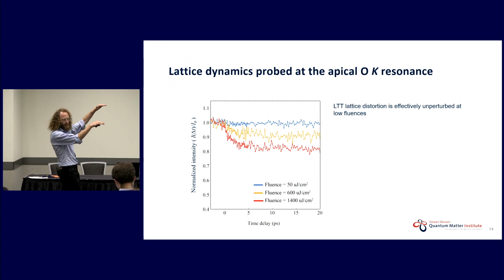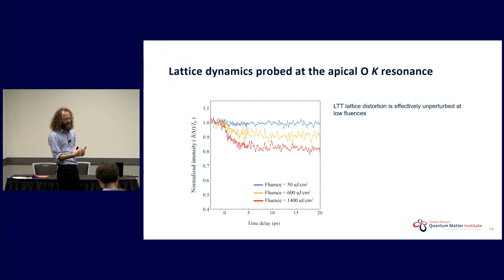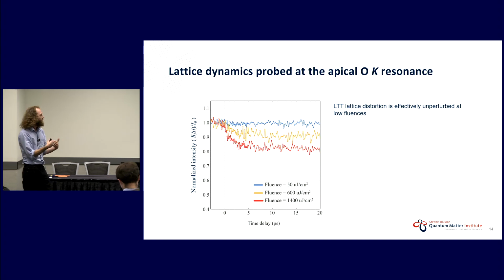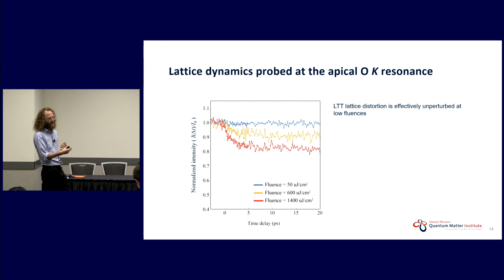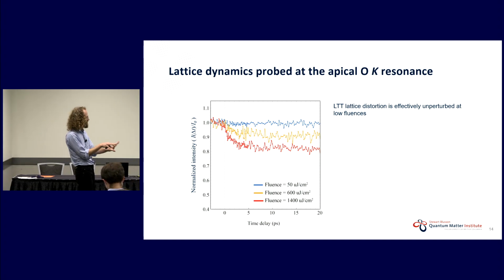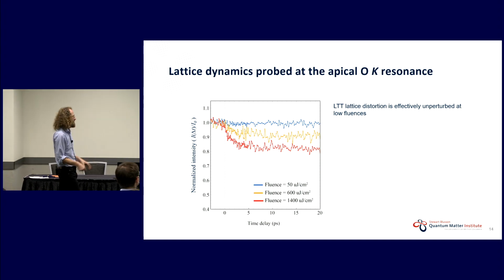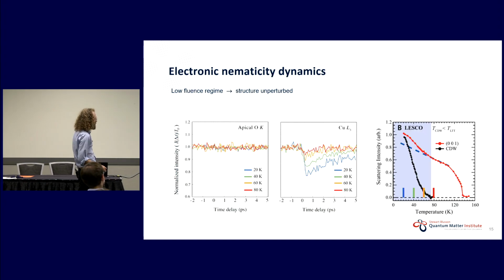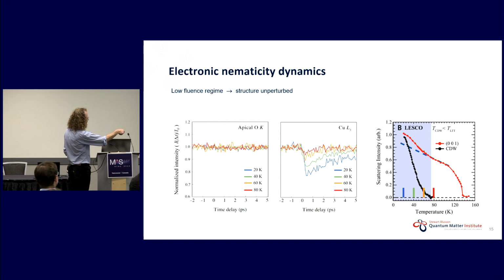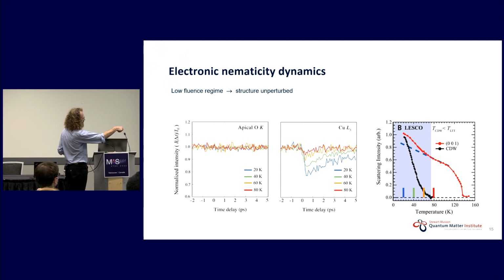Now we're going to go to the copper L3 resonance, or the planar oxygen K resonance, where we have sensitivity to the low energy physics of the copper O2 planes. And hopefully then we'll still be able to perturb the electronic degrees of freedom with this low fluence and know that we're exclusively touching those electronic degrees of freedom. And so that's what we do. And here you can see, as a sort of control case, the apical oxygen resonance. Again, no effect at this low fluence.